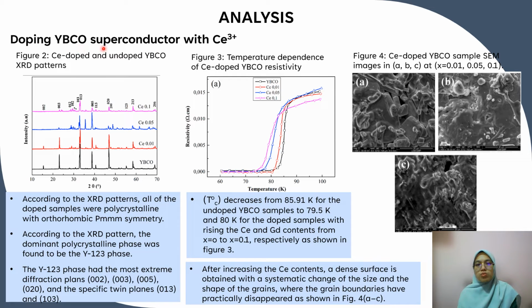First, doping YBCO superconductor with Ce3+. Figure 2 shows the Ce doped and undoped YBCO XRD patterns. According to the XRD patterns, all of the doped samples were polycrystalline with orthorhombic Pmmm symmetry. Also, according to the XRD pattern, the dominant polycrystalline phase was found to be the Y123 phase.